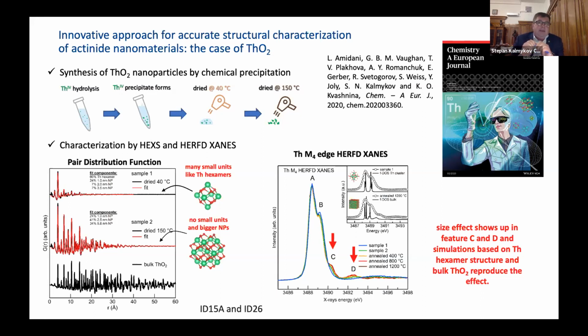Using PDF, we can make the fit components, and we can define, for example, that the as-prepared sample, dried only at 40 centigrade, has 60% of this polynuclear species of thorium hexamers. We have about 24% of 1 nanometer size particles, 7% of 2 nanometer particles, and 7% of 3.5 nanometer particles. This is a very powerful technique that can give us information about the size distribution in this complicated mixture of different particles.